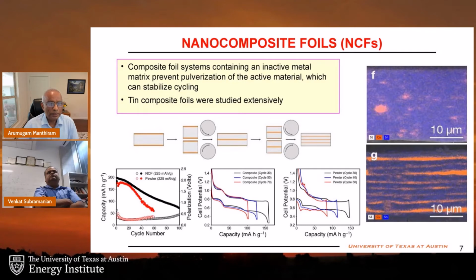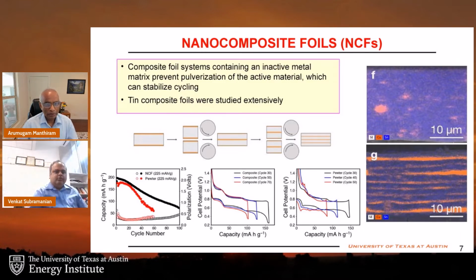So the process is very simple. It will have an inactive matrix, like for example, aluminum. In that you disperse tin, that's one approach. Or you can have aluminum itself as an active material without anything else. So here you make an ingot of the alloy, then you cold roll it, and then after cold rolling, you can cut and fold or stack and cold roll. If you do it repeatedly many times, you can have a nice dispersion of the active material and the inactive material. This is the beauty with this technique. Very easy to do, just cutting, rolling. That's all we do.